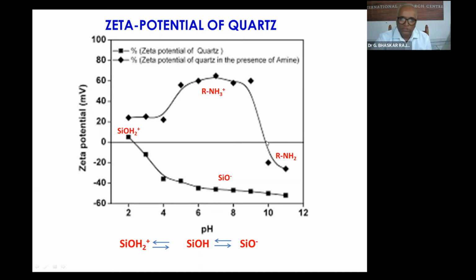This particular application is in flotation. When we want to separate the silica particles, we use this primary amine as a reagent. This primary amine will coat the surface of the silica particles, and when the air bubbles pass, the silica will be separated from the remaining particles. So it is useful in the separation of silica from the other materials. Suppose you have other materials in this as well, they will also have different charges.